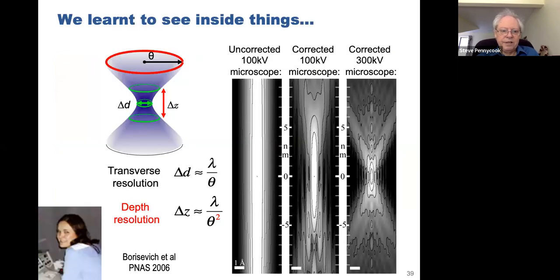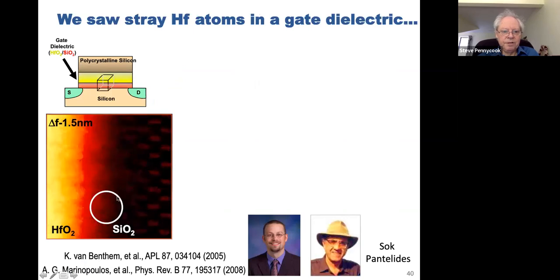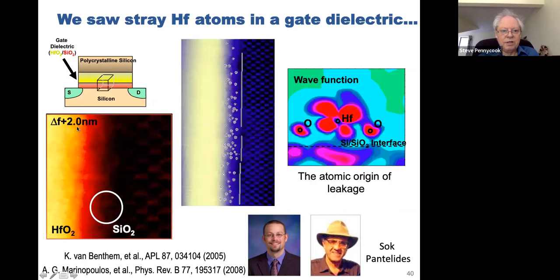The other thing we realized is the depth resolution, as mentioned in the previous talk actually. If you increase the angle, then depth resolution increases as the square of the angle. So it's a dramatic increase, especially if you go to a 5th order corrector. And now you can probe different heights of the sample. You can focus on the top and the bottom and look at the circle here. This is Klaus van Benthem. Focusing through the dielectric, there we are. The hafnium atom comes into focus and disappears. We're just going 0.5 nanometer at a time here.